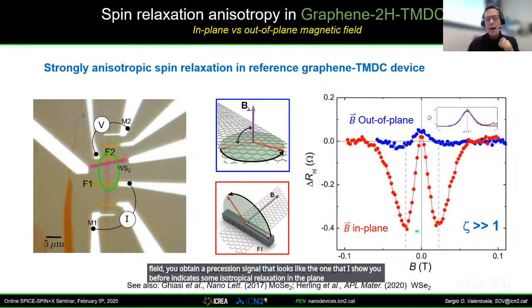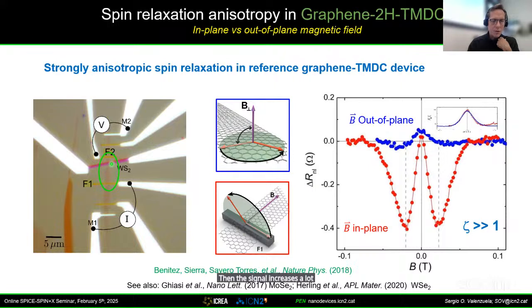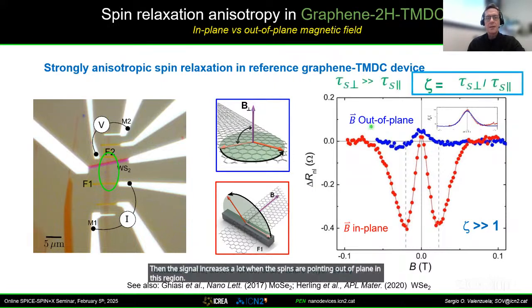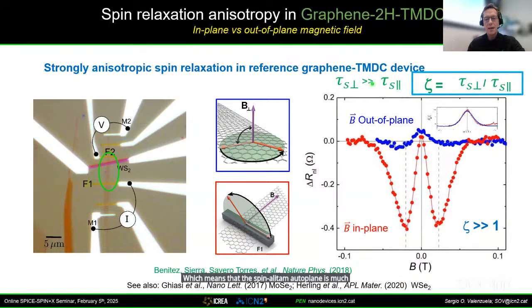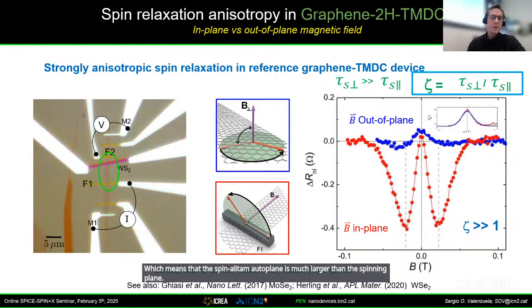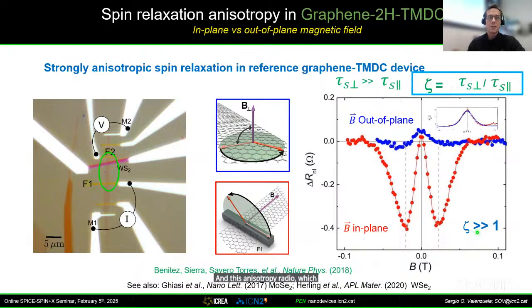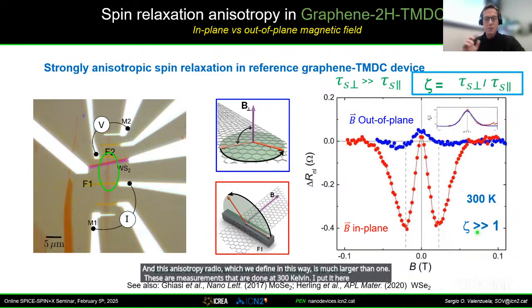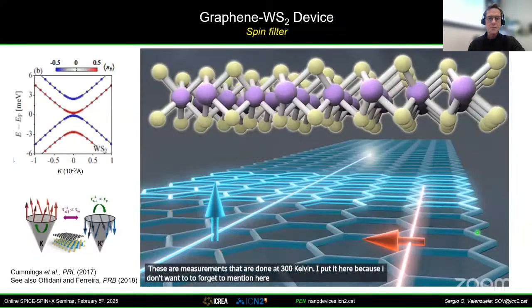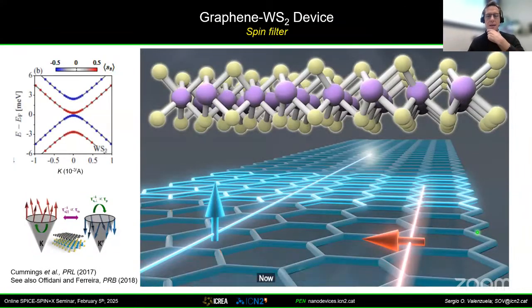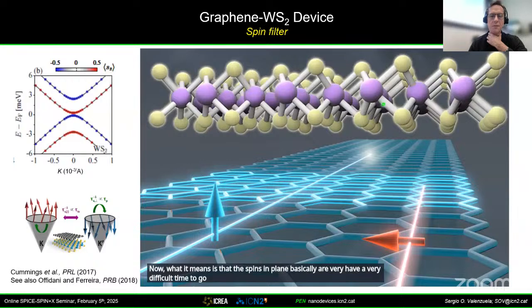However, if you take spins out of plane, then the signal increases a lot when the spins are pointing out of plane in this region, which means that the spin lifetime out of plane is much larger than the spin lifetime in plane. And this anisotropy ratio, which we define in this way, is much larger than 1. These are measurements that are done at 300 Kelvin. I put it here because I don't want to forget to mention it. It's all room temperature. Now, what it means is that the spins in plane basically have a very difficult time going through the region that is proximitized by this material, but the spins out of plane go much more easily. You can create some sort of spin filter.